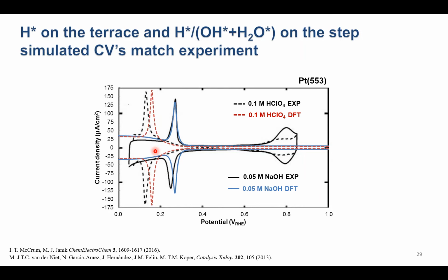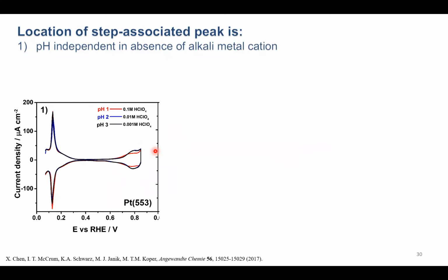I'll say this is work that I did during my PhD with Dr. Janik. And it was around this time that we started collaborating with Mark's group before I moved there for a postdoc. And one of the students in his group, Xiaoting, performed a really interesting set of experiments that I think strongly supports and elucidates the important role of the alkali metal cation. And so the first thing that she did is she measured cyclic voltammograms on platinum 553 in varying pH electrolytes without adding the presence of an alkali metal cation.